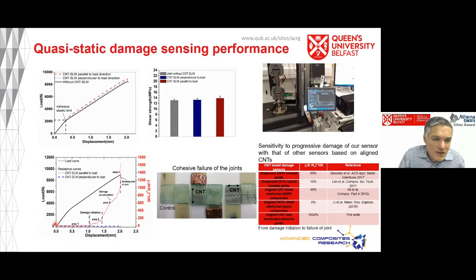And what we know then is if I draw your attention to the red curve, we can measure the change in resistance, and before any visible damage at the joint, we start measuring a change in resistance, and that accumulates as the damage accumulates.